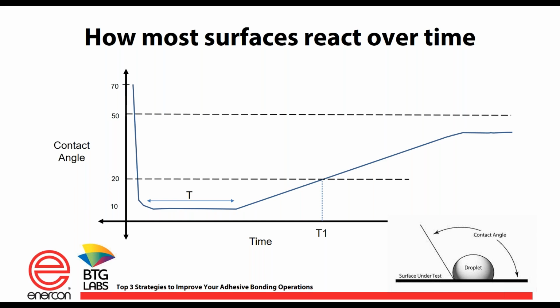So this is a chart that we came up with. If you start at a relatively high contact angle over here and you treat on the left-hand side, it's going to drop down to a steady state portion that I've marked at time T. Now, how long is T? T is going to vary with every surface and every different treatment method. So the only really good way to find out what T is, is to actually test your surface in our lab.